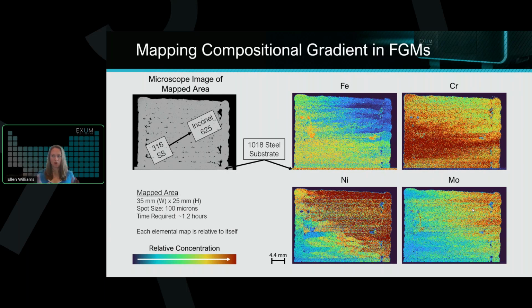So again, room for improvement in terms of the porosity and optimizing the parameters, but an excellent proof of concept to show that Massbox's broad scale elemental mapping, we're looking at a 35 millimeter by 25 millimeter area here that was done in about an hour, can be very useful when it comes to process control and developing new advanced manufacturing techniques and new advanced materials, especially where we have a chemical gradient.